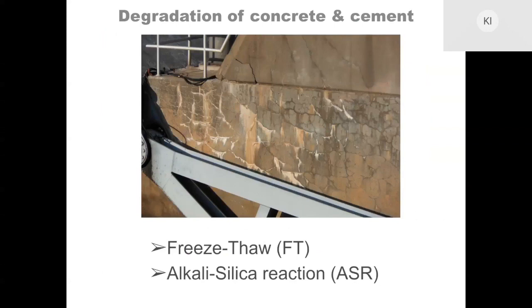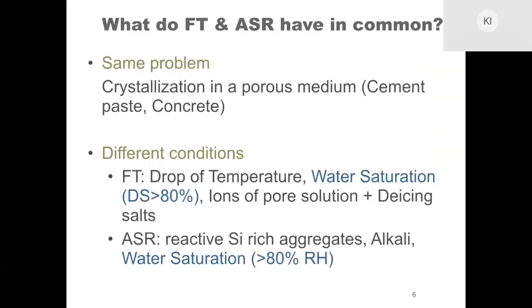Both of these problems have a common feature. We basically have a crystallization problem in a porous medium. The porous medium is the cement paste and the concrete. And in both cases, we have a new phase forming in the porous network. For example, in the freeze-thaw, we have the water crystallizing. And in the case of the alkali-silica reaction, we have the formation of a gel due to the silica-rich aggregates that exist in concrete. So this is the common feature of these two durability issues, but they have a little bit different conditions for why this is happening.